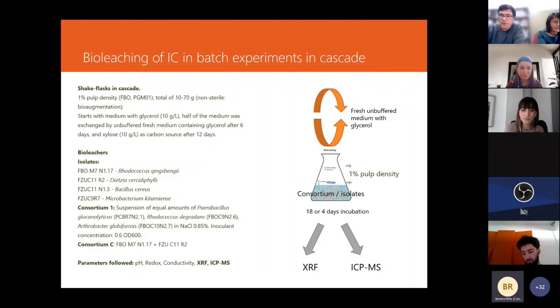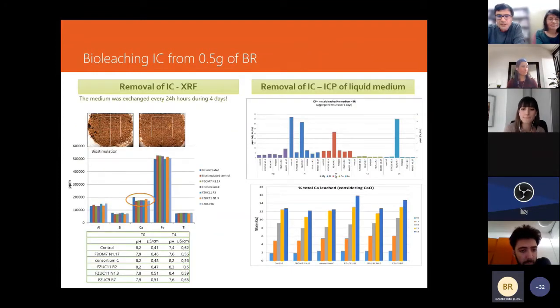So the parameters that we followed were metals dissolved by ICP, and we also followed the change of solid residue by XRF, and we also used a colorimetric method to follow dissolved calcium. And if you can change to the next slide, please. So all the experiments used 1% pulp density, and of course we also followed the pH and the conductivity. So here are the results that were obtained with bauxite residue with the isolates.